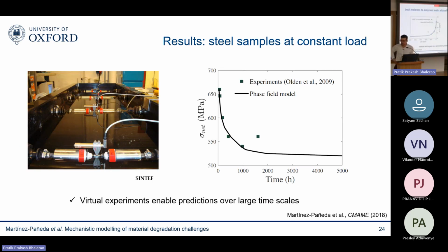These are experiments done in Norway that were a bit more interesting. What they did here is they immersed duplex stainless steel samples in a seawater bath and subjected them to a constant load. And then they measured the time to failure of each of the samples. Since they were testing different loads, they had different times to failure. But as you can see, all the samples failed relatively early. So they weren't able to identify what is the critical threshold load below which you will not see embrittlement.